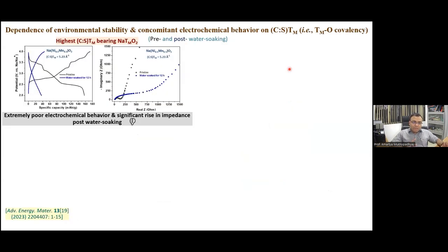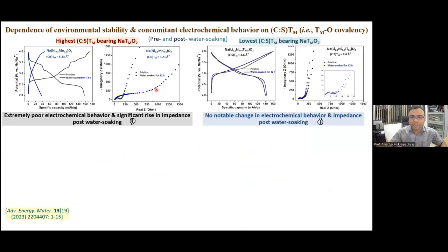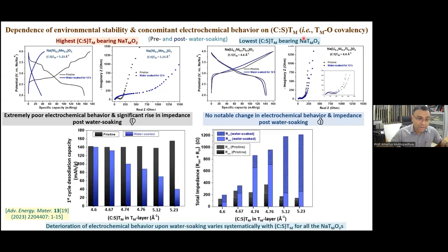Now, when we do electrochemistry in sodium half cells, we can see the highest charge to size bearing material, which was highly unstable upon exposure to air, after water soaking, the capacity is almost negligible as compared to the pristine material without water soaking, and the impedance increases drastically. By contrast, the lowest charge to size ratio bearing material retains its capacity, and the impedance hardly increases upon soaking in water, which proves that not just in terms of the structure, but also based on the electrochemical performance, the lowest charge to size bearing layered transition metal oxide is highly water stable.